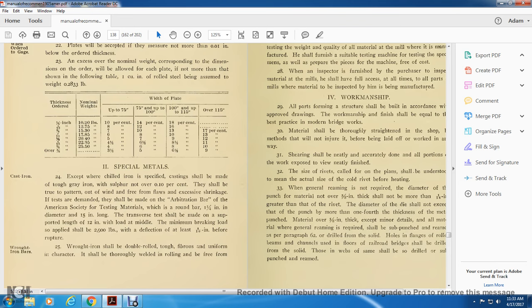Except with the shrinkage test, the test shall be made with the arbitration bar of the American Society for Testing Materials, a round bar of 1 1/4 inch in diameter and 15 inches long. The transverse testing should be made with a support length of 12 inches with a load in the middle, of the minimum breaking load applied of 2,500 pounds with a deflection of at least 1/16 of an inch before the rupture.